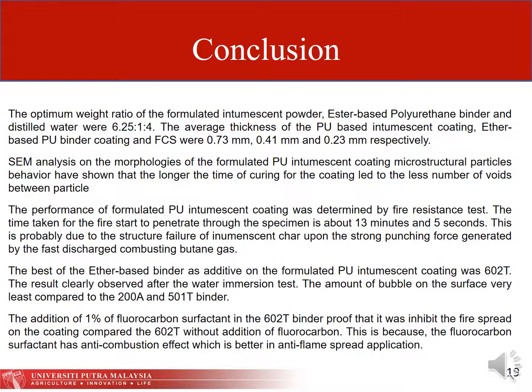The performance of the formulated PU intumescent coating was determined by the fire resistance test. The time taken for the fire to start to penetrate through the specimen is about 13 minutes and 5 seconds. This is probably due to the structure failure of the intumescent char upon the strong punching force generated by the fast discharge of combusting butane gas. The best binder as additive on the formulated PU intumescent coating was 602T. The result was clearly observed after the water immersion test. The amount of bubbles on the surface was very least compared to 200A and